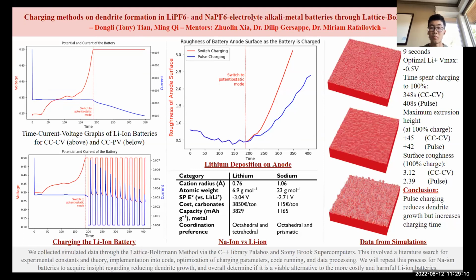of lithium batteries. Despite their advantages, one major hurdle for the adoption of sodium-ion batteries is that dendrites grow and form on them faster than on lithium. We conducted a literature dive and began modifying the lithium-ion model to instead simulate a sodium-ion half cell while simultaneously optimizing the parameters. By running the sodium-ion model, we hope to gain novel insight on the formation of dendrites in sodium-ion batteries and how different charging methods may prevent it.